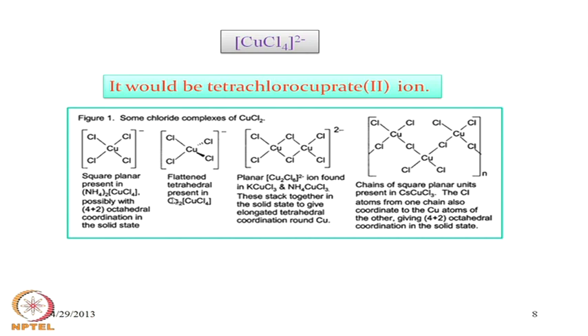So, if we have cesium, which is a bigger cation, the individual species will remain in a flattened tetrahedral structure, and we do not get such sharing of octahedral species. Similarly, one type of bridging can be obtained in some potassium salt or ammonium salt of KCuCl3 or ammonium CuCl3, with a mix of these two, we get the potassium ammonium salt of Cu2Cl6. And these stack together to give an elongated tetrahedral geometry around this particular copper, and we have the corresponding sharing of this. So, we get a chloride-bridged dimeric form.